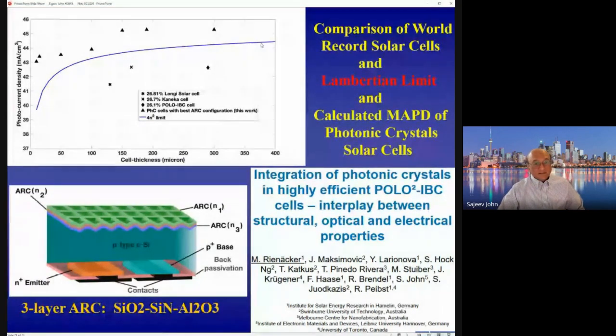The blue curve is the Lambertian limit, so you can see that all these solar cells fall below the Lambertian limit for photocurrent density. The wave interference-based light trapping structures that we've shown are shown above here, starting from 10 and 15 microns, 50 microns, 100 microns, and then 150 microns and thicker. You can see that even at 15 microns, we are getting a predicted photocurrent density that's well above the Lambertian limit and already comparable to these world record cells. And if you apply this wave interference to even these thicker cells, there's a great deal of room for improving the photocurrent that could be generated in these cells by a more efficient light trapping mechanism.